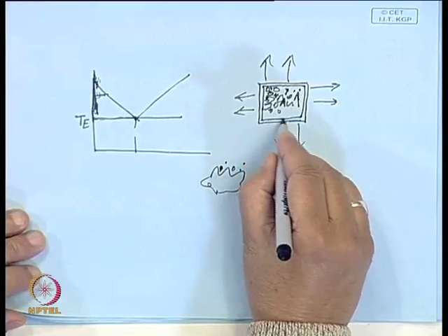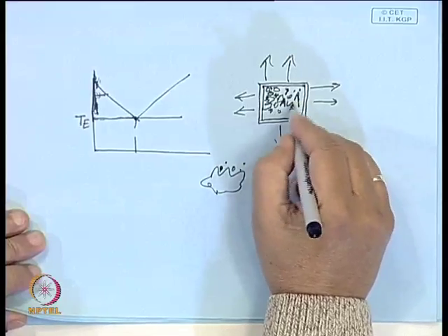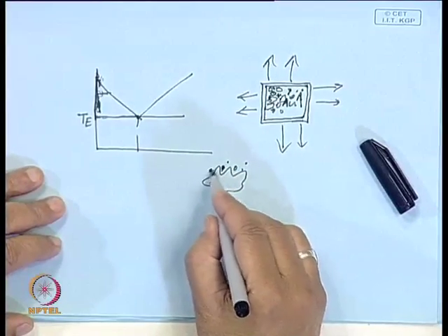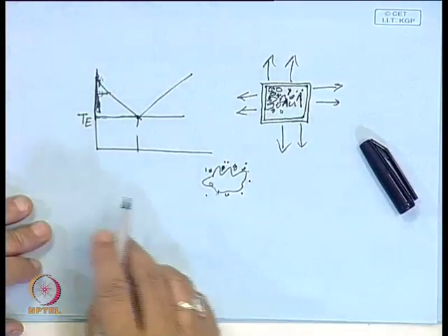So in reality, this is the defect-free, segregation-free region, and air has segregated in the central portion, and this is what you get when you solidify alloys as well. When you solidify steel in a large mold, the steel will have dissolved gases, these gases will go to the center, and in the meantime if the top has solidified, the gas cannot come out. So in the central portion you will get gas porosity, and in fact these porosities will be present in the interdendritic channels. And this is a type of segregation.